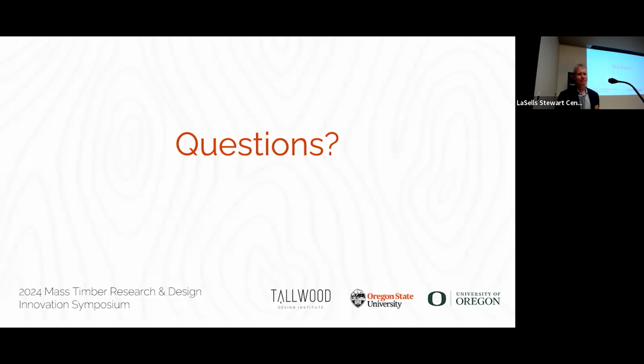Chris, I'm just wondering if you actually monitor the moisture content in the CLT when you pour the concrete. We don't actively monitor it, but we know it beforehand, and then we wait till it gets back to where it was before we start. How long does it take? Several months. And the problem is it's only at the surface that we can get access to anyway. But that's one of the reasons to even get a creep test started before you can get to equilibrium conditions, it takes a long time. It's a very paint drying process.